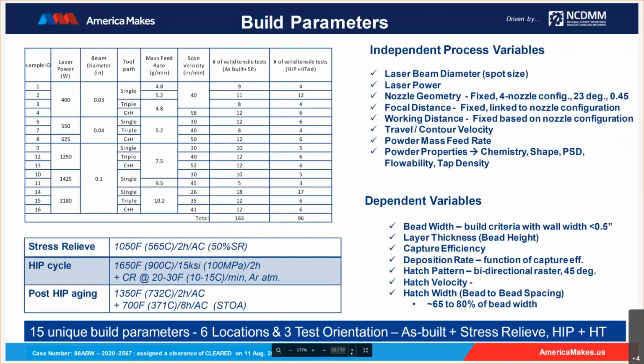For example, the independent process variables included, from the build process standpoint, power, speed, strategy, etc. From the post-processing standpoint, it included heat treatment, and when it came to tensile testing, the specifics of specimen extraction, be it surface condition of the gauge length and tensile gauge orientation relative to the horizontal, were varied. The table also includes the number of samples we've tested for this particular feature. So in the as-built and stress-relieved condition, we tested around 163 specimens, and in the hipped and aged condition, we tested around 96 specimens. Next slide, please.